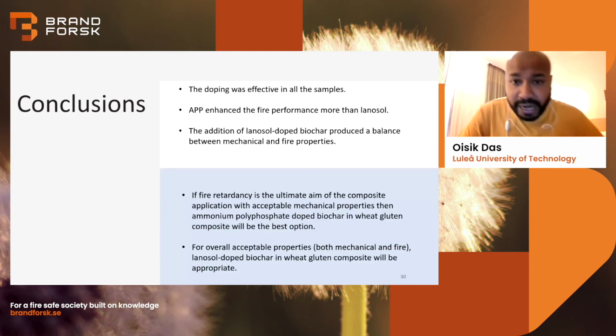So to end the project and the results, we have been able to find an effective doping method, which was a thermal doping method, which means that the biochar was successfully functionalized. And we have found that APP doping is a better fire retardant compared to Lanosol when it comes to fire performance. So if you are looking for a composite that is extremely fire safe, then we choose biochar doped with APP in wheat gluten made by compression molding.